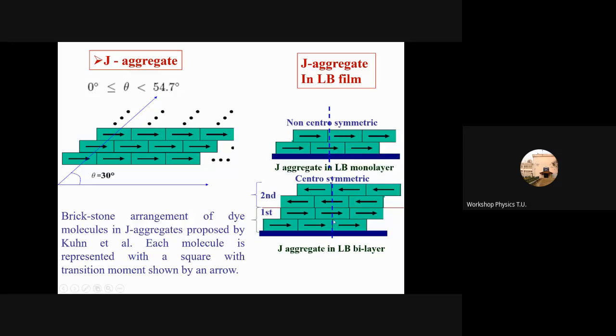And you see, if you join a line here, in the first one above, it's a layer of two molecules, but it's a single layer. If you draw an imaginary line, it's not symmetric. But if you have two layers and you draw a line along the center, you can see the whole system is symmetric. So if you prepare a J aggregate of a single layer, maybe a stacking of more than one molecule, but it should be a single layer, this is important, then it is a non-centrosymmetric structure, and it is SHG active.